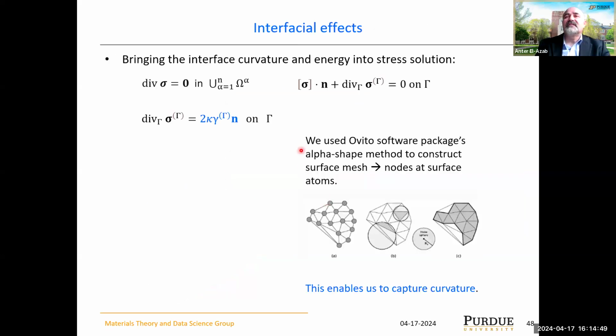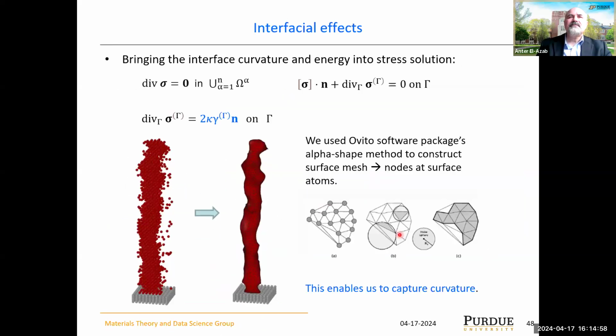We're also making another improvement in this. The pillars do have irregular shapes, as you see here. And these irregular shapes are kind of associated with curvature, and the curvature gives rise to so-called capillary effects. In macroscopic or macro scale elastic materials, we don't care much about capillary effects, but in nanoscale systems, the capillary effects are actually important and they have an impact on the strain in the system. So this is also being integrated currently with that framework.